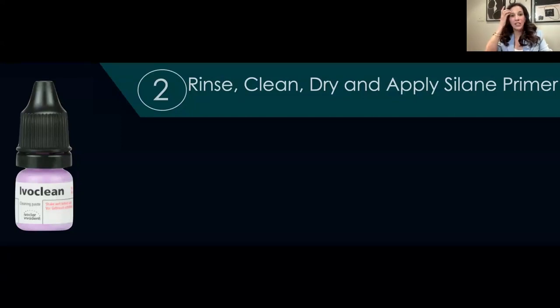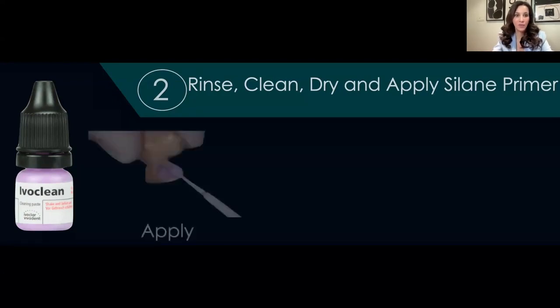Alternatively, you can etch the veneer chairside. So that's a choice that you should make. I personally like to etch my veneers after I try them in chairside. So then you'd want to rinse, clean, dry the veneer and apply the silane primer.